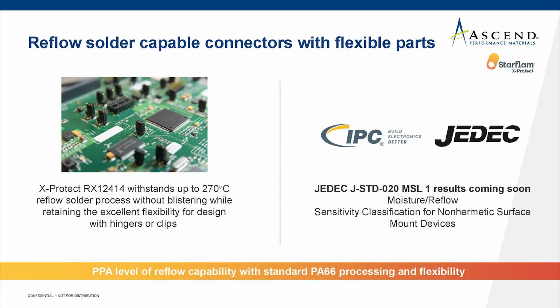But even more critical for polyamides, you don't want to generate any blisters. There is this standard called JEDEC J-STD-020, where materials are rated by their moisture sensitivity level, or MSL. And MSL1 is basically the best performance you can achieve, where a component can be stored under humid conditions and still not exhibit any blisters when going through the reflow solder process. Starflam X-Protect achieves that level, compared to regular PA66 type of materials. Other materials that can achieve that level would be PPA or PPS.